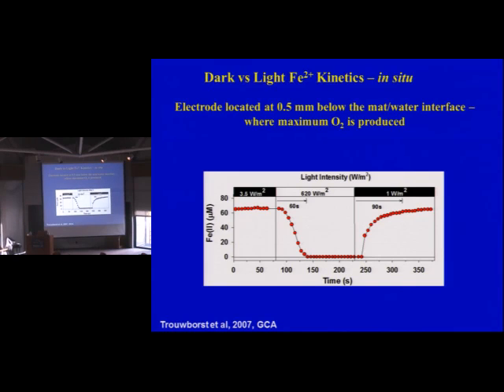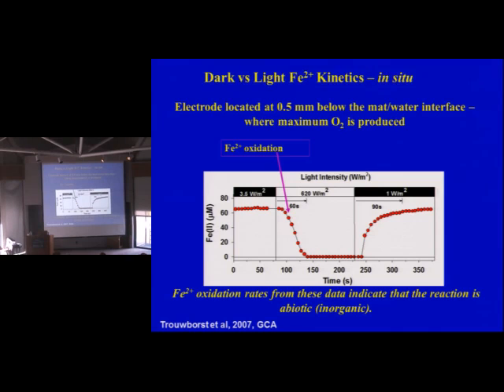And this is 65 micromolar iron, too. All right? So what you see is the iron oxidation. You let it sit for a while, and then you go dark. And then, by the way, the iron oxidation rate here is totally inorganic, because if you look at it from the temperature, it had to be extrapolated a little bit because people haven't really done that at 55. But this is totally abiotic.